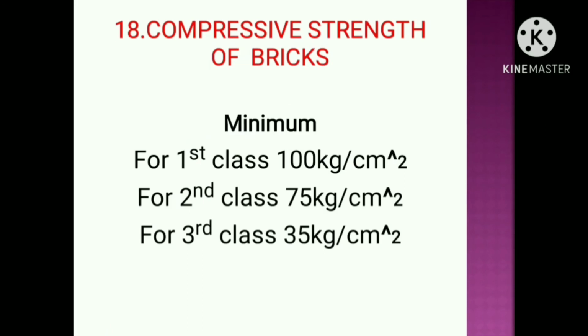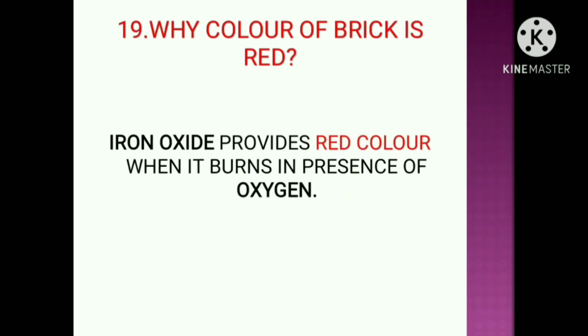What is the compressive strength of bricks? So minimum compressive strength of first class bricks should be 100 kg per centimeter square. For second class it should be 75 kg per centimeter square, and for third class it should be 35 kg per centimeter square. Why the color of brick is red?